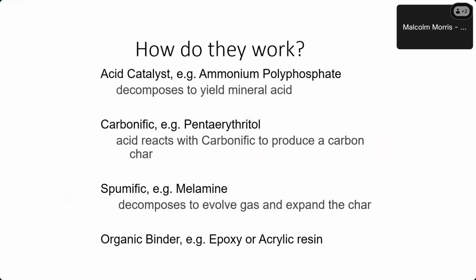How do they work? Well, the key raw materials in classic intumescent formulations are an acid catalyst such as APP, ammonium polyphosphate, which decomposes in the fire situation to yield phosphoric acid. That phosphoric acid then reacts with what they call a carbonific, which is pentaerythritol. Typically, that's a complex alcohol. The acid reacts with that to dehydrate it and form a huge amount of carbon char, soot effectively.